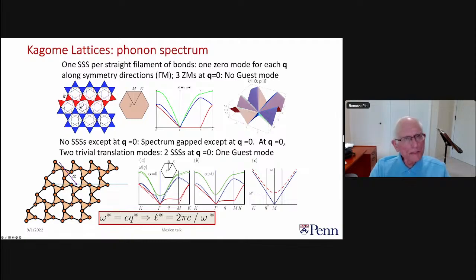So basically, we have a number of bonds which is proportional to the perimeter of the system, bonds going across there. Each of these straight lines has a state of self-stress and therefore a zero mode. And the zero mode is each mode along this knife edge that we looked at earlier as a function of Q running along there. So here are the zero modes going this way, and their origin are these straight lines, states of self-stress. Now, when I twist the system like this, we lose all of the straight lines. So that means that we no longer have any of these straight line zero modes. The Q equals 0 is slightly different, but mostly what we're saying is still true.